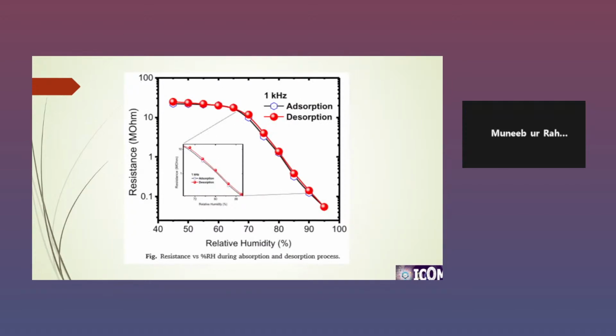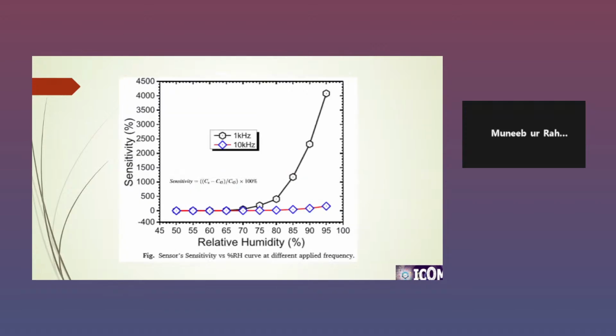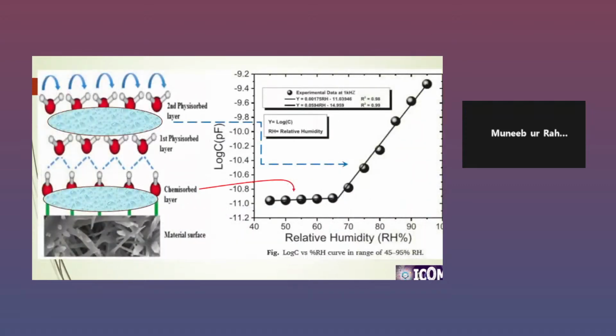This is the hysteresis loop of our device, which shows a narrow hysteresis loop. For an ideal device, the hysteresis loop should be minimum. So this is the sensitivity of our device. At 1 kilohertz, the sensitivity of our device is quite high above 70% RH. This is the conduction mechanism, and this is the curve fitting.